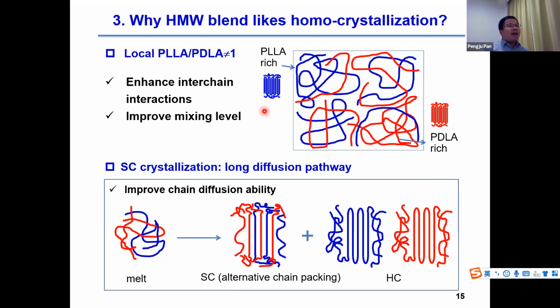As we talked about before, high molecular weight blends like homocrystallization and don't like co-crystallization. It is still unknown why high molecular weight blends don't like co-crystallization. We think there are two possible reasons. One is that the mixing of L and D polymer may not be completely homogeneous in the melt. Somewhere has more PLA chains and somewhere has more PDLA chains. These PLA and PDLA rich domains would crystallize in homocrystal.